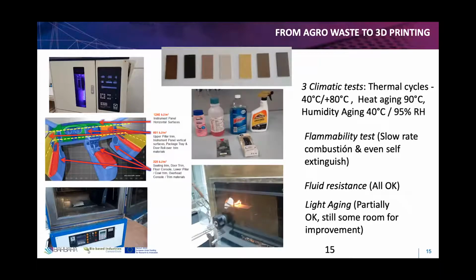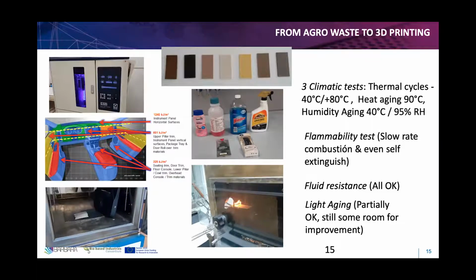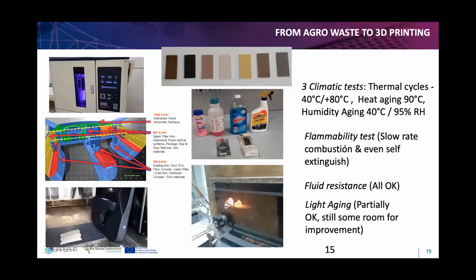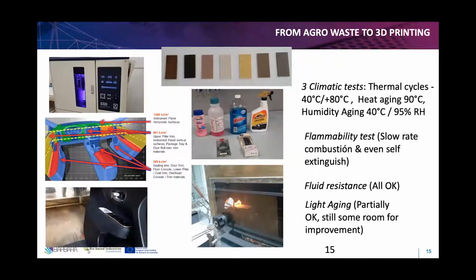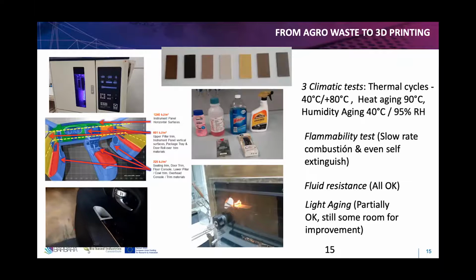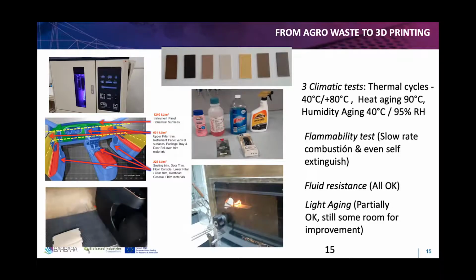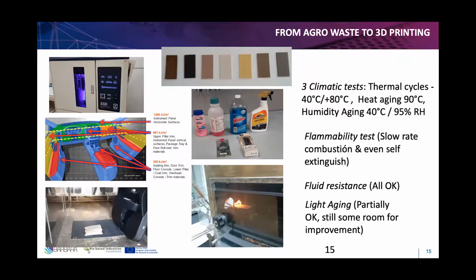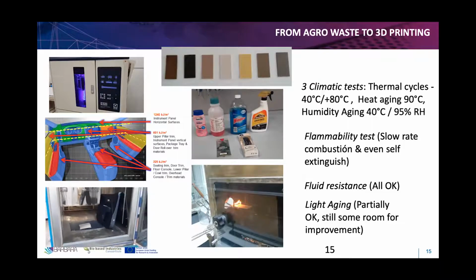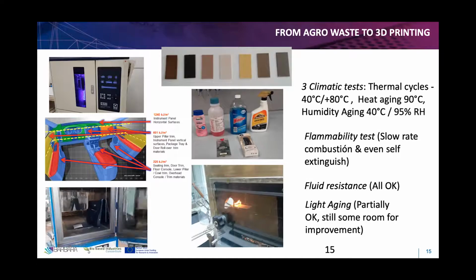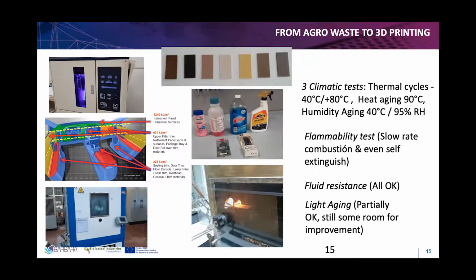So finally, for the automotive validation, the materials passed three climatic tests, then a flammability test, a fluid resistance test using different chemicals that we could use to clean our car, and the light aging test. The different materials passed all the tests. There were some gaps regarding the fastness in the light aging, but it was not so bad due to the fact that we were not using at any time UV blocker additives that typically these parts use. So that would be the room for improvement of these materials anyway.